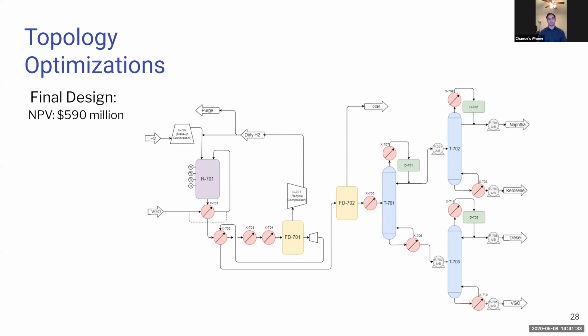So some of the safety considerations that we had, you can see on this picture E-701. That's the preheat exchanger for the feed. And if the reactor would start to run away, if we didn't have a bypass around this exchanger, we wouldn't be able to control the temperature. So one of our safety considerations was to add a bypass around the preheat exchanger, so the relatively cool VGO could go directly into the reactor bed and quench it. That's one of the safety considerations that we had, as well as just the material construction safety considerations.